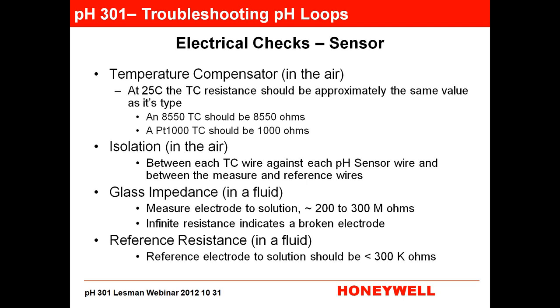So you can check that just by using a multimeter, put the sensor in air, and then just check across the two temperature compensation leads. At about 25 degrees C, your temperature compensator should be about the value that it's defined as. So if you have an 8550 TC, you should see about 8,550 ohms. Now, if you're not right exactly at 25 C, it'll be a little bit off, but it's going to be very, very minor. If you have a PT1000 TC, you should see 1,000 ohms. If you have a PT100, 100 ohms, etc. So that's how you can test the TC.